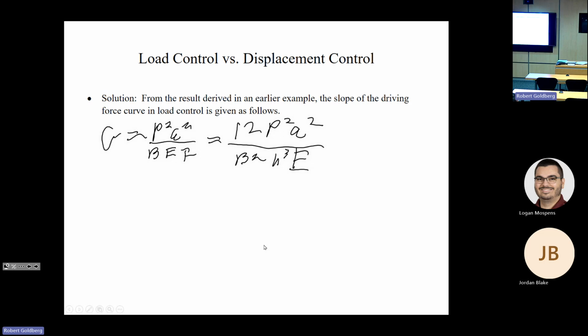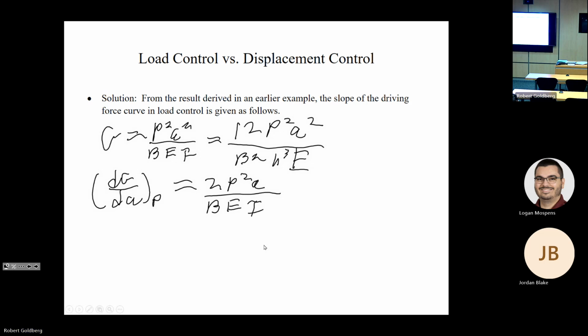And for the case of load control, we can say that the derivative of the strain energy release rate with respect to crack size, holding P constant, is, when we do the math, 2 times P squared times a divided by B E I. We just use this expression when we did the derivative. And if we compare to our initial definition of the strain energy release rate, we can say that it's twice the strain energy release rate divided by the crack length.